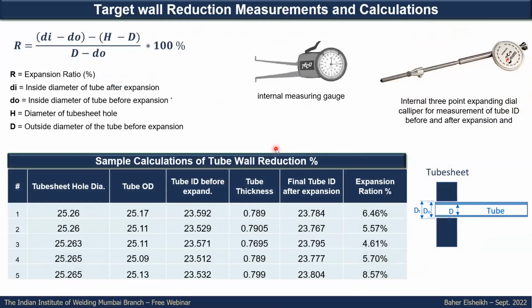This is how the methods for how to measure the internal tube bore, and this equation from TEMA, how to calculate the measured or the expansion ratio. And this is an example for some of the calculation. We measured everything: tube sheet hole, tube OD, tube ID after expansion, and tube thickness. And those measures, as we said, should be the actual tube and hole dimensions measured during the mock-up, not something from the drawings or from the recorded value.